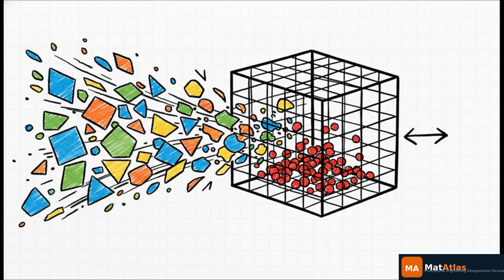To pull this off, we need direct lithium extraction, or DLE. This relies on a whole suite of advanced mechanisms like nanofiltration, ion exchange, and electrodialysis. But a real standout here is ion sorption, using inorganic ion seeds like manganese oxide spinel structures. Think of these like molecular bouncers at an exclusive club. Because of their incredibly specific lattice structure, they selectively capture only the lithium ions from a chaotic soup of sodium, magnesium, and calcium, letting the rest of the brine flow right on past.